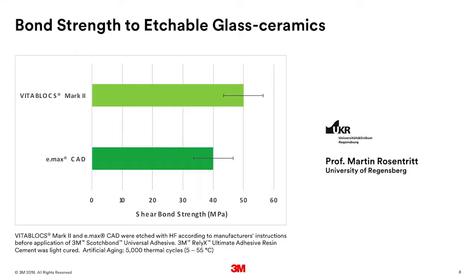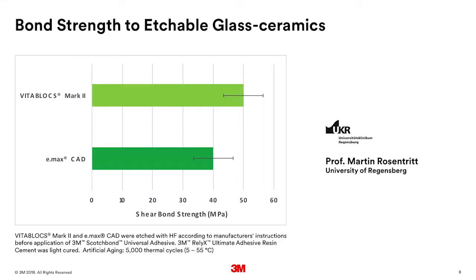So is that bond strong enough? Do we have to worry about water contamination or water over time? That's a really good question. When we study that, and as shown here, Dr. Martin Rosentritt at the University of Regensburg did a study where we aged the bond. What we do is prepare a sample, bond a button to it, and then put it in 5 degrees C water, and then move the samples into 55 degrees C water, hot, cold, and we go back and forth for a number of cycles. And then after we've stressed it, we measure the shear bond strength. And what we see here is a very high bond strength after thermal cycling, of 40 plus megapascals, to two very common etchable glass ceramics, Vita Mark II and e.max. That's evidence that the bond is very durable and hydrothermally stable in the oral environment.